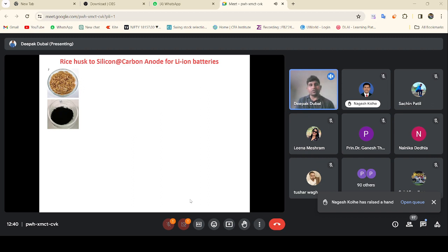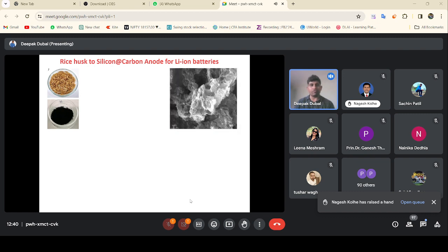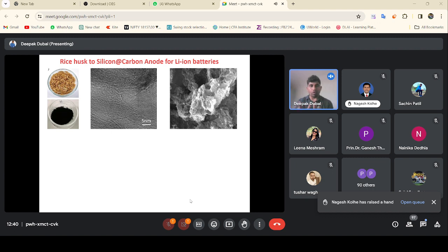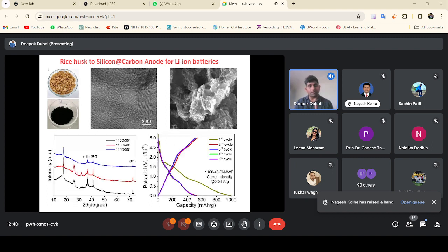But in the end, we decided to try the same strategy in a microwave. That was very impressive: she could form graphitic carbon materials from this organic waste, and at the same time she converted the silicon oxide into silicon. This is very impressive because in general, if we try to reduce silicon oxide into silicon, we end up with amorphous silicon. But this time we got highly crystalline silicon.